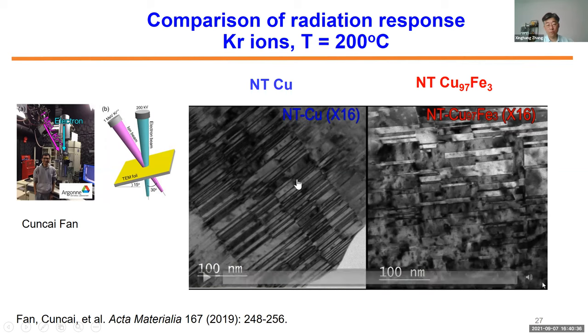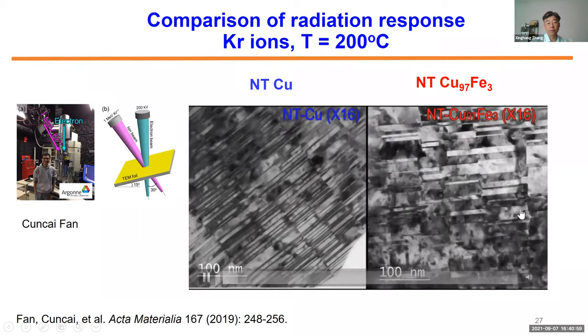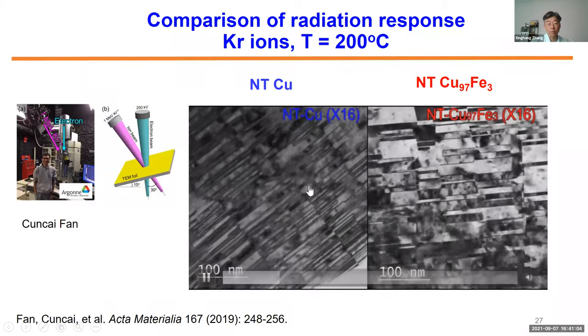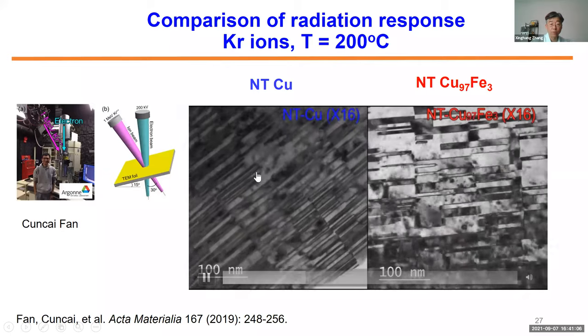And you notice the twin thickness is somewhat different. So these twins are somewhat finer in pure copper. They're maybe on the order of 5 nanometer or so. But on the other hand, nanotwinned copper iron, they indeed have a little bit larger twin thickness. And if you perform this radiation under krypton ion beams at 200 degrees Celsius, you see some very interesting phenomena. First of all, this defect changes relation to these defect loops. But if you notice what happened to the twin boundary, there's pretty drastic twin boundary movement or detwinning.